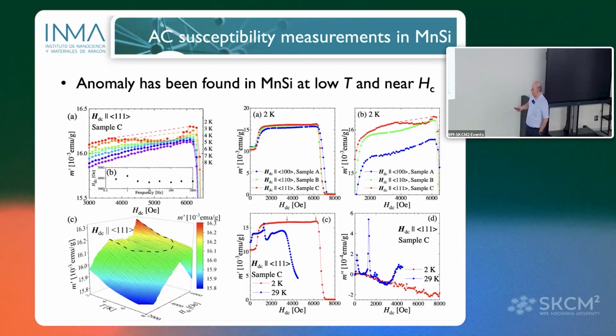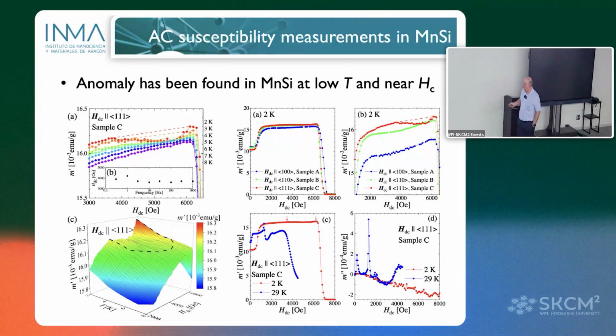Also, in the skyrmion lattice area, at 29 Kelvin, the in-phase magnetization has a strong signal that is not observed in the low temperature anomaly. And in the skyrmion lattice area, the out of phase has a strong absorption that is not observed at 2 Kelvin. That means that the anomaly is different from a skyrmion lattice.